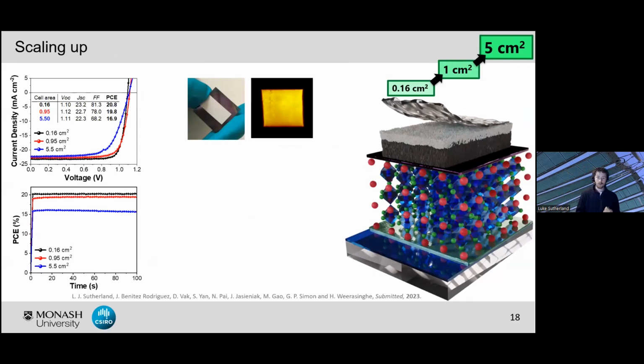And really, we can see the benefit of the CIP here in applying uniformly distributed pressure across the whole surface area of our electrode, which, as we can see by the photocurrent map, then results in uniform photocurrent generation, again, across the whole surface area of our device.